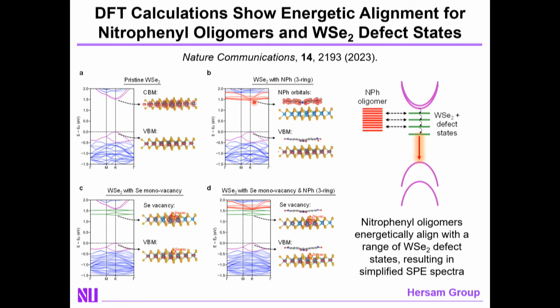And if you have a distribution of molecular orientations and oligomeric identities, then what you will achieve is a band of states that are coming from the zero-dimensional side of your heterojunction that reside just below the band edge of your tungsten diselenide. The net effect is that the emission from all of these states near the band edge become quenched, or at least become dark.